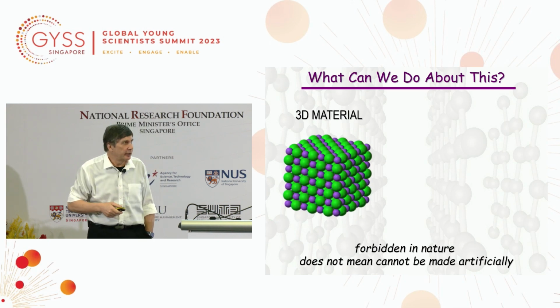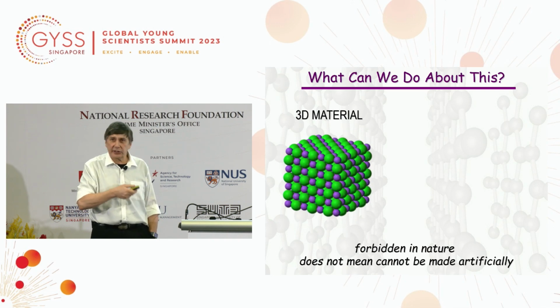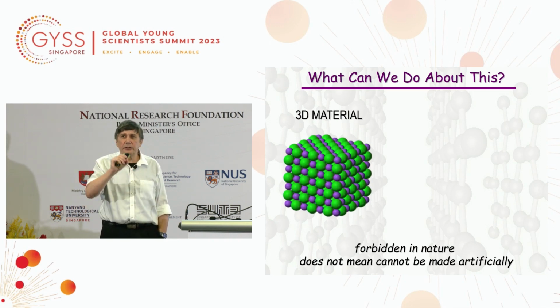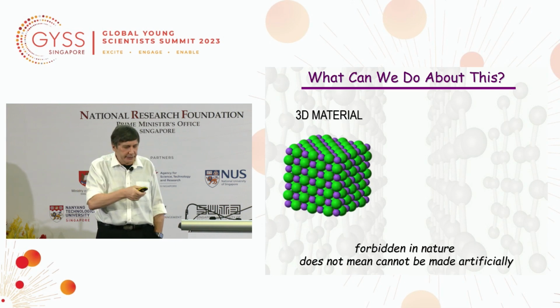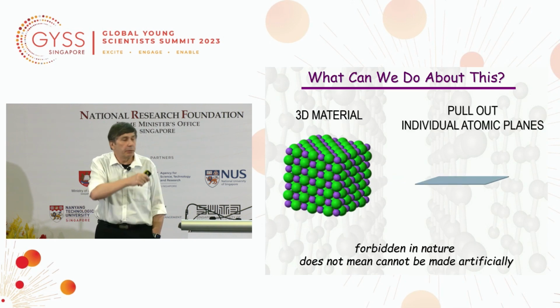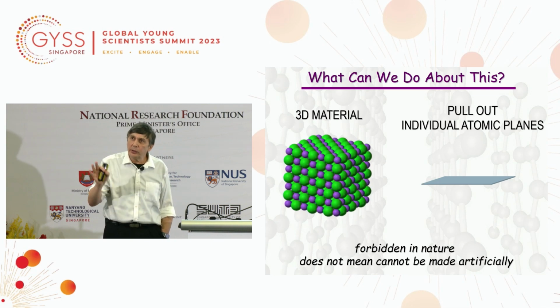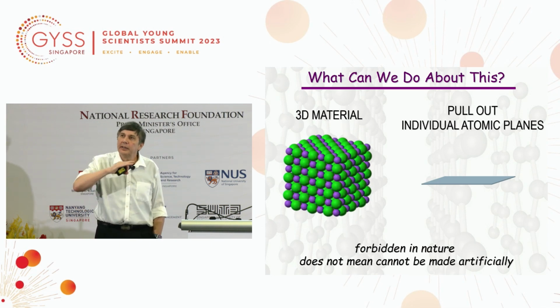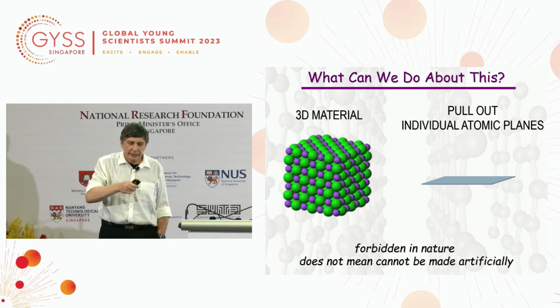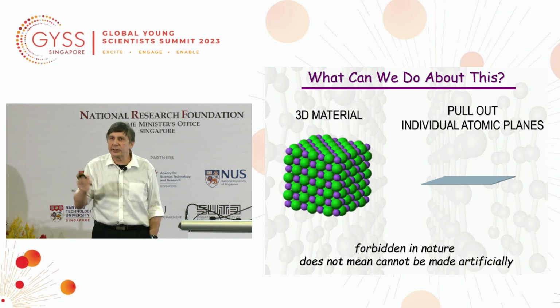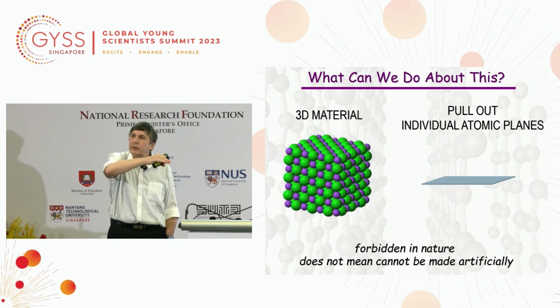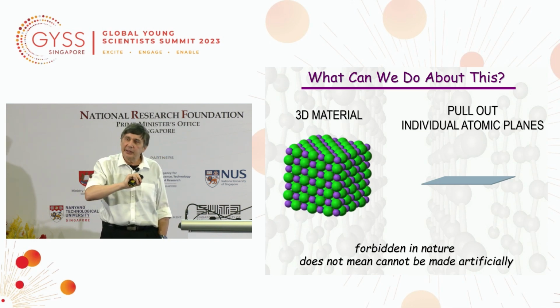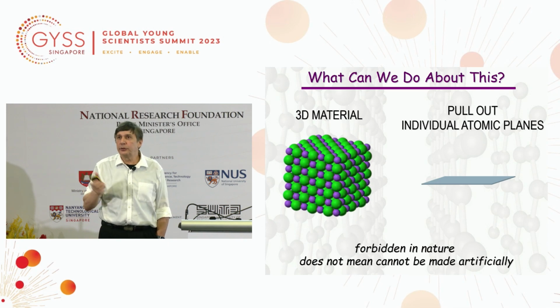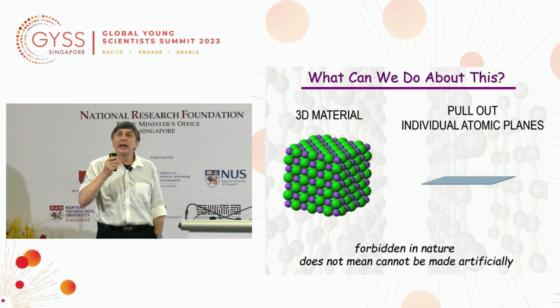Essentially we took a three-dimensional material, graphite, or you can take any other material, and imagine that you have very tiny tweezers and you pull an individual atomic plane out of this three-dimensional material. Those physics theorems, which you can't break during growth, you can still get around in this experiment, because you start with a three-dimensional material grown at very high temperature, and then at relatively low temperature, our room temperature, you pull out an individual plane, and there is no theorem that forbids it. But the mentality was not there to do this kind of experiment.